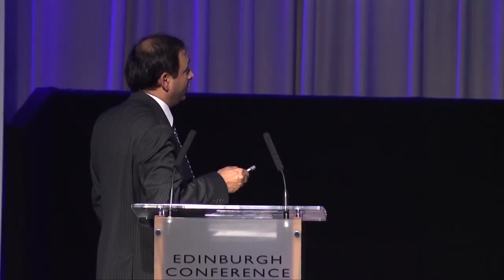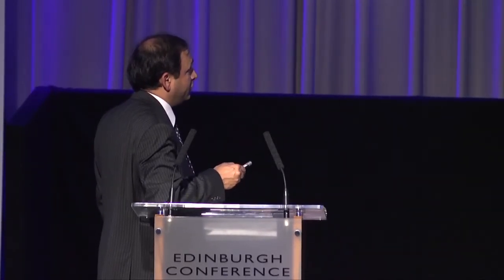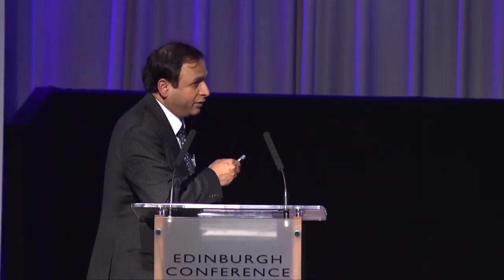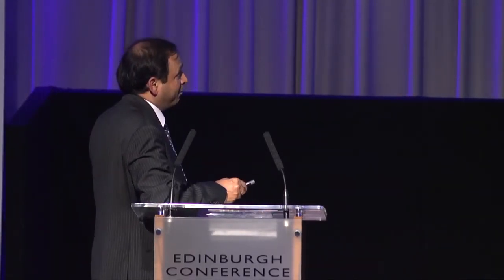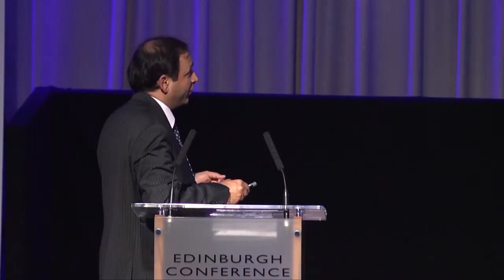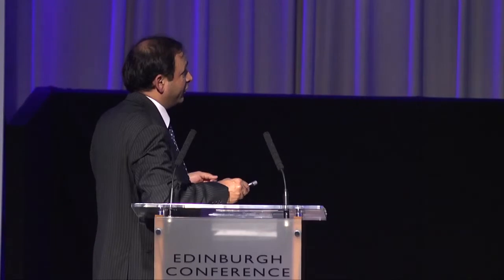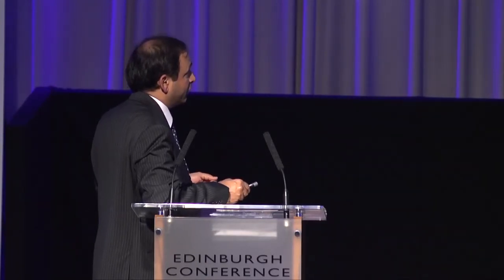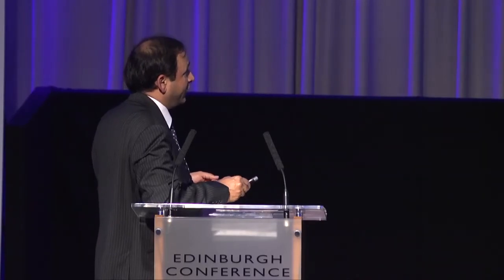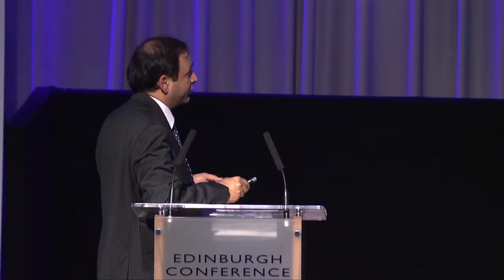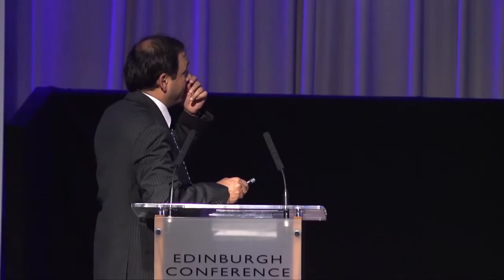You can see here these amorphous silicon materials were actually 1/100th of the thickness of crystalline silicon, but they can absorb the same amount of light coming from the sun. But the efficiency figures which I had taken were about 15% at module level, which compares a little less than what crystalline silicon has already achieved.